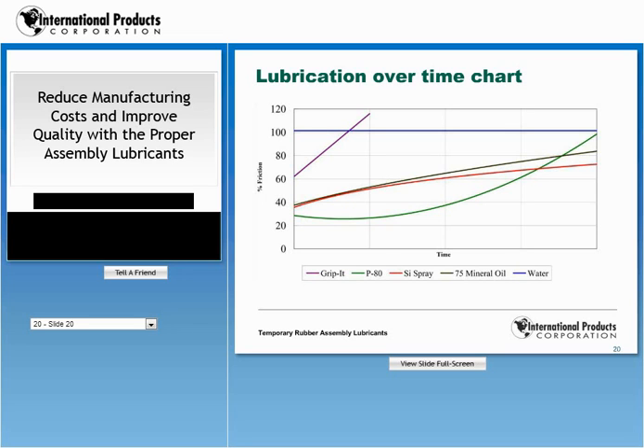But notice what happens as it dries. It actually increases above and beyond the dry assembly force. So again, if we go back to the tire example, if you install the tire using P80 Grip It, you need 60 pounds of force. However, after it dries and you try to remove it, you're going to need anywhere between 110 to 115 pounds. So that Grip It does provide some lubrication, and it also provides a tacky residue to promote the parts to stay together.